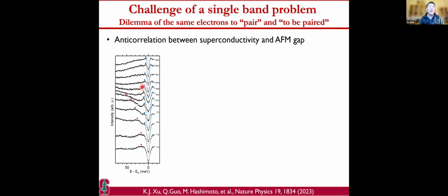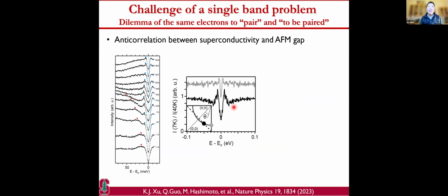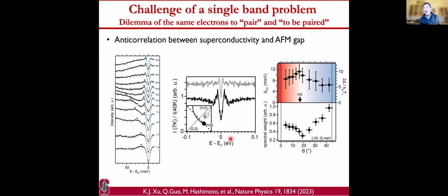I've shown you this peak showing up only below TC, and this peak now shows a momentum dependence. If I plot the feature at the anti-node, you can see that the gap is smaller, the coherence peak is also smaller. On the other hand, when I plot the feature at the magnetic hotspot, you can see that the gap is bigger and also the coherence peak is bigger. Okay. So here, as you go along the Fermi surface, you can see the big features show a maximum gap. That means that's where the pseudogap is the largest.